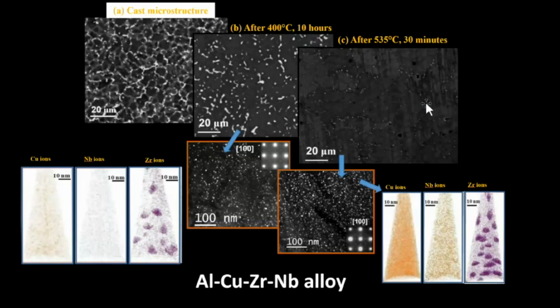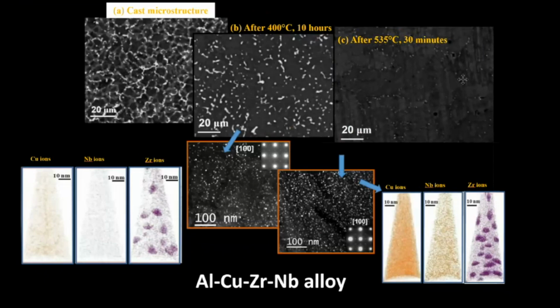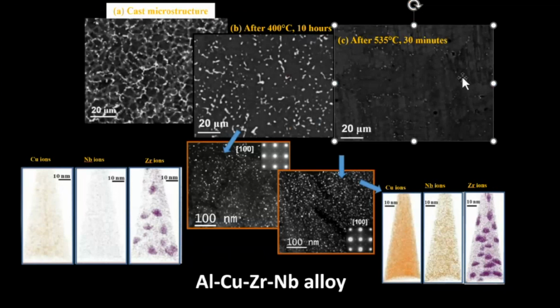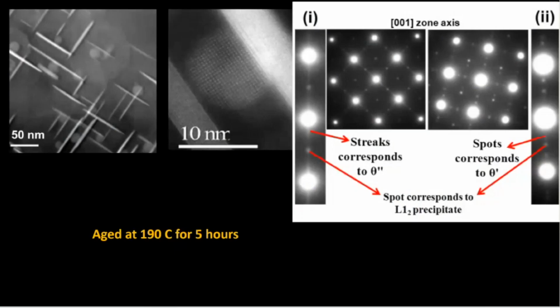We upquench because of the segregates that you see at 400 degrees centigrade 10 hours on the left-hand side. They are all aluminum copper segregations, sorry. So we want to get rid of this. We do 30 minutes at 535 degrees centigrade, and they vanish. Basically, all the copper segregation goes away, but the ordered precipitate does not go away. As you can see in the picture below, and even in APT, we find that, in fact, they remain as they were after the heat treatment. So this shows you what happens now if I age it.